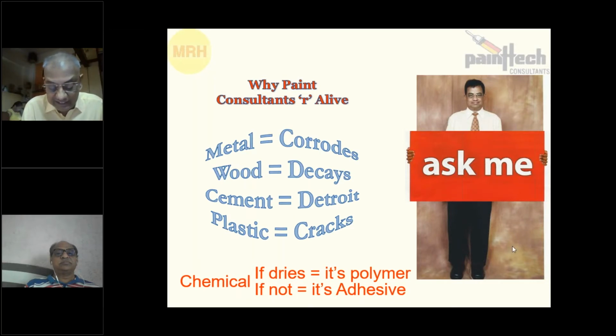For 10 liters of H2O addition - in fact, I shouldn't say this as a water-based additive manufacturer, I am the first person in India to manufacture water-based additives - but I should tell you, for 10 liters addition of water, no additive is even needed. If you want to add 10 liters of water to enamel paint, add it freely. No additive required, just keep the viscosity at 70 seconds.